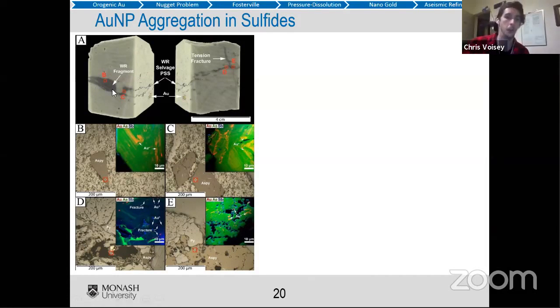live in it. So if we look at B, which is our least deformed or cataclased or pressure dissolved volume of rock, we have gold that lives in a crystal structure. It's not obviously associated with any sort of crystal chemical zoning, but it is living in the crystal structure. And you can tell that because the distribution of gold is parallel to the crystal faces. It's not in big clumps. It seems pretty washed out. Then we have sample C, which is a little bit pressure dissolved. Again, we have gold that's in the structure and then maybe a little bit in a fracture here.